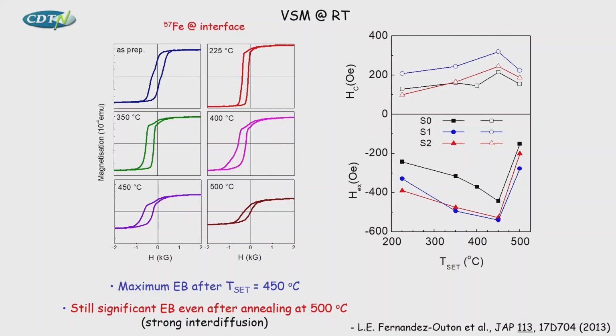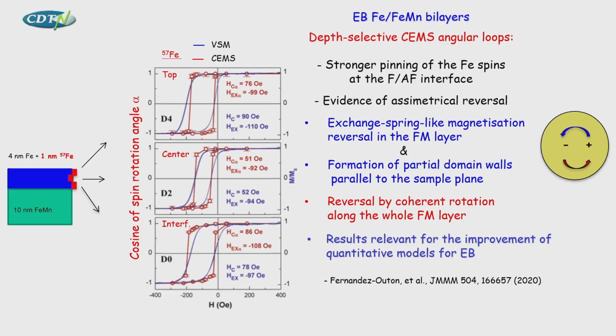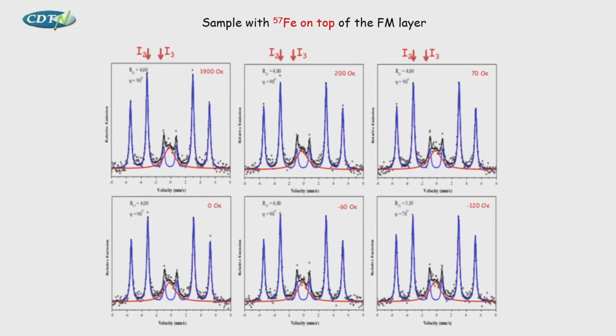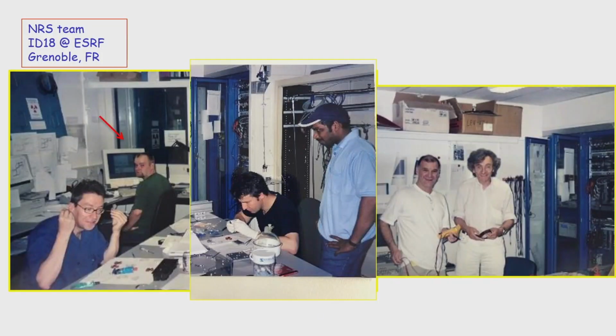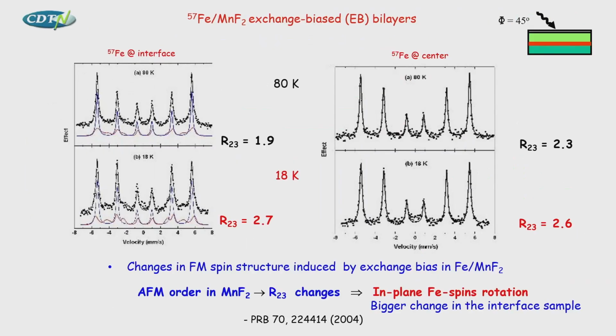So you have done two spectra at two different temperatures. Which one do you mean? The first system, it's iron on, if I remember, manganese fluoride. This one. So when you go to low temperature or high temperature, you have changed the 2 and 3 lines, and you assume this effect is completely due to the coupling between the iron spins. My question is, when you do the temperature dependency, you also have internal strain that increases.